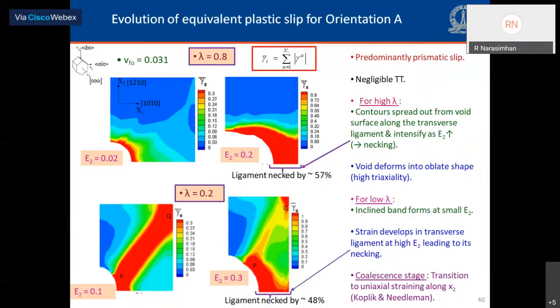These are contours of plastic slip corresponding to orientation A for large lambda of around 0.8 stress ratio. The top figure, and the bottom figure is for lambda 0.2, that is low stress ratio. Now, in this particular orientation, prismatic slip is predominantly active, and we can see in the top contours, at low strain, prismatic slip starts developing around the void surface, and as the macroscopic strain increases, the prismatic slip engulfs the entire transverse ligament, leading to its necking. As you go for lower stress ratio, the bottom images, we see that initially the prismatic slip develops as an inclined band, cutting diagonally across the unit cell.